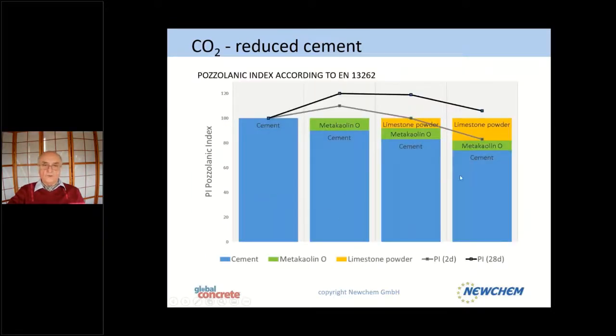So here we have 4 different mixes we made. We made a cement; 100% is the compressive strength which we compare. It's the pozzolanic index. We have here 2 graphs showing. The first one, the lower one, is the compressive strength compared to the pure cement after 2 days. And you can see that with metakaolin replacing cement, you can increase your compressive strength by about 10%. Then you can add some limestone powder to make it cheaper, or other pozzolanic materials, and get to the same 2 days compressive strength as the original cement. If you add much more limestone, you come beneath the values of the cement.